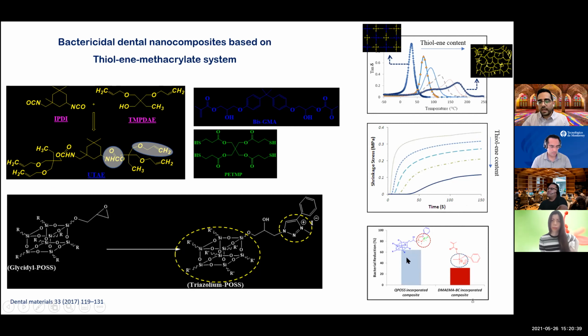And finally, we have the antibacterial activity. At the same time, we prepared and synthesized a monomer as a model, a quaternary ammonium with the aliphatic structure, and the other one with the aromatic structure. We can see that the nanoparticles functionalized with the triazolium functional groups show a higher degree of bactericidal activity, and I think it was a good result for us.